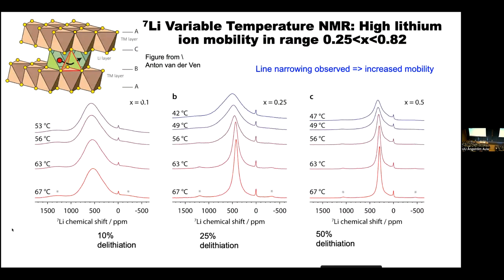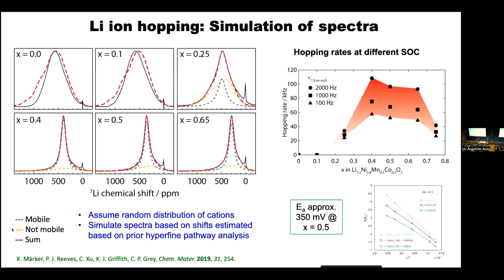You get hops from octahedral sites through the tetrahedral sites to the octahedral sites in these structures. As you pull lithiums out of the structures, you create more vacancies and the mobility increases. And so we can develop, or Katerina developed, a model for extracting the hopping frequencies from the changes of the line widths. And from looking at this as a function of temperature, you can get the activation barrier. And so the bottom line is, between about x equals 0.25 and x equals 0.75, you have very fast lithium ion hopping in the layers.